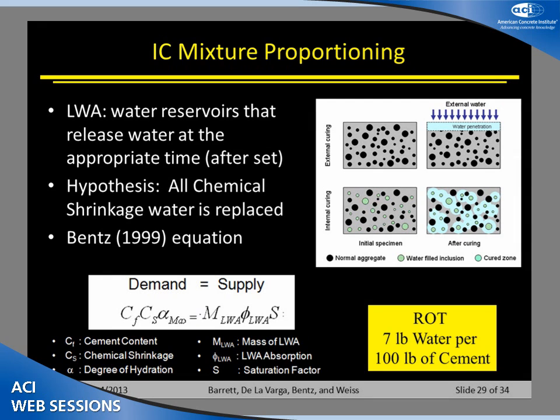We put water on the top of the surface, or we put a film on top of the surface, but in a really dense concrete, this water can only penetrate so far into the material. The approach that we're trying to use is instead of essentially just providing water from the surface, we can hide water inside of porous inclusions. We can hide water inside of the aggregates, and when that water is needed, it can be drawn out of lightweight aggregates, hydrate the system, and can provide some of the beneficial components that we would want to see here.